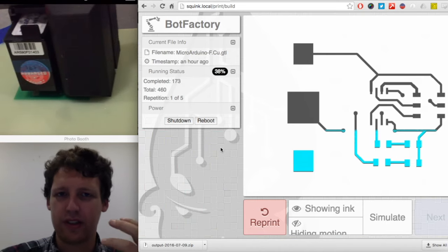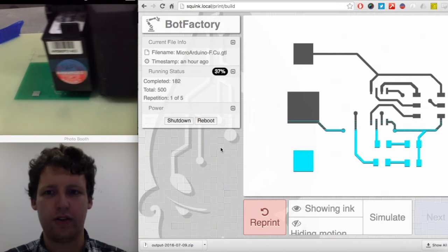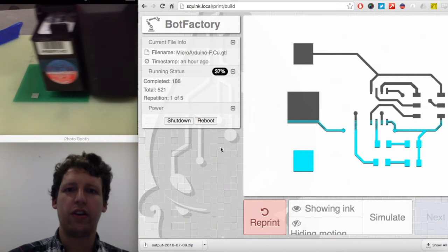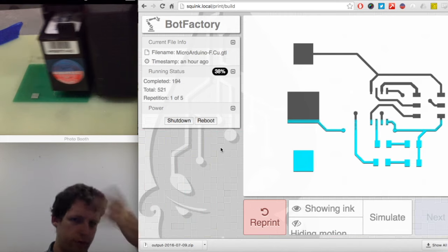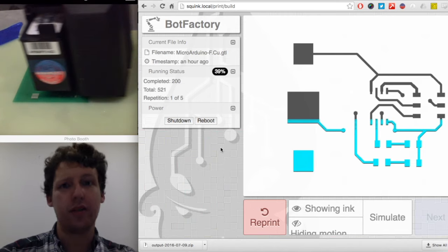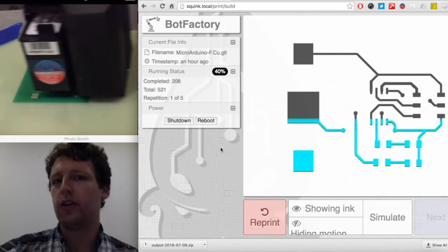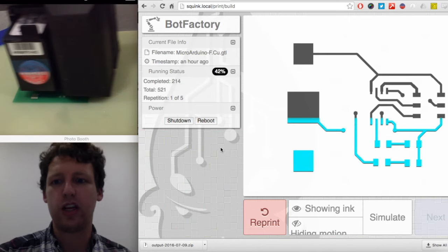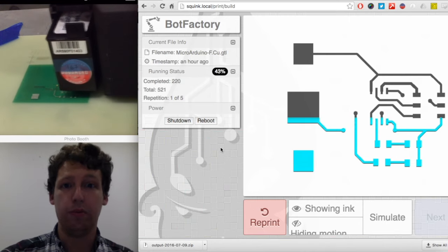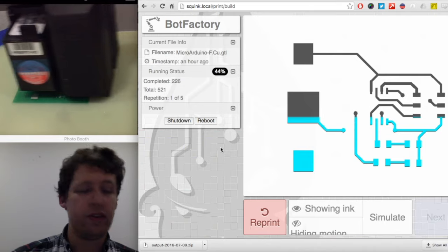Essentially what's happening is the material is deposited onto the surface. It immediately starts melting. The carrier fluid is evaporated, leaving nothing but silver nanoparticles that under the 110 degrees Celsius environment immediately begin to sinter. That's the beauty of this material.